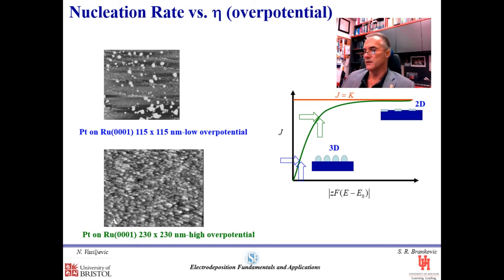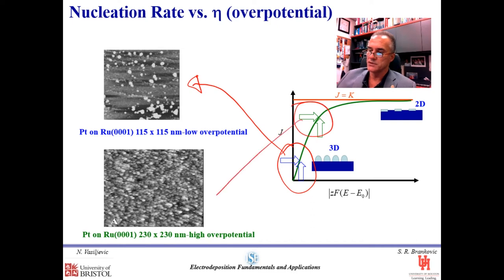Here's a real example when we look into the effect of the value of the overpotential on the nucleation rate and the outcome of the electrodeposition process. For the low overpotential, we can see that the nucleation rate is quite small, and the deposit sporadically forms without covering the entire surface of our substrate. However, for much larger nucleation rates and applied overpotentials, we can have uniformly forming deposits with much higher nucleation rates on the surface. Obviously, our interest is to form deposits which are really uniform, covering the surface. We would like to nucleate, or design our process, where the nucleation step is supported by the large overpotential.